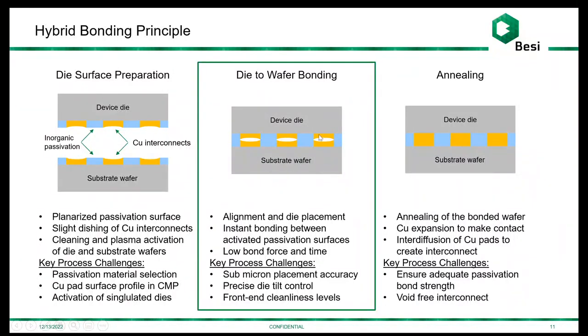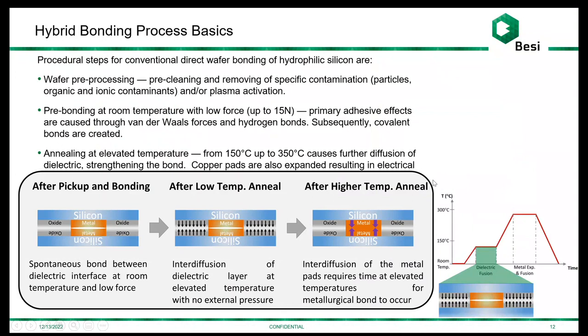After we create this oxide bond, then we go through an annealing step, and I'll give you a little bit more detail on that here in this slide. So typically we do this annealing in two steps. We have a first step wherein we ramp up to a lower temperature in the range of 150 C, for example. During this part of the process, we're creating an interdiffusion of the oxide layers. Initially in the bonding process, they're stuck together basically with van der Waals forces, but in this annealing step, we're actually causing interdiffusion to occur.